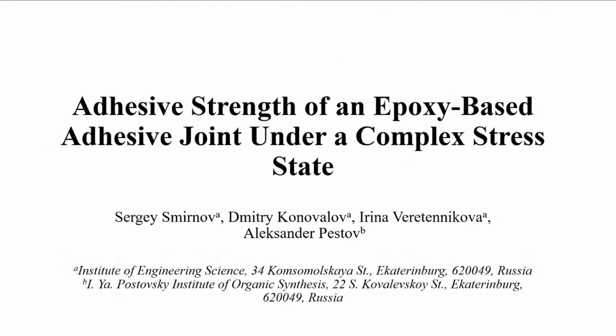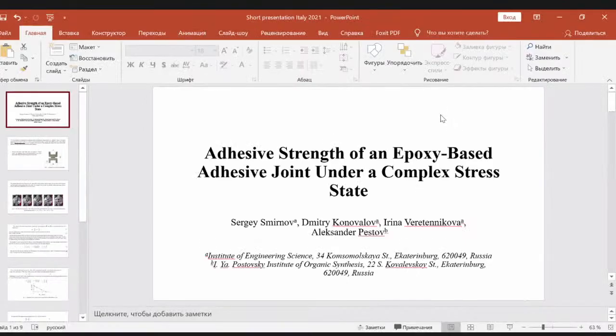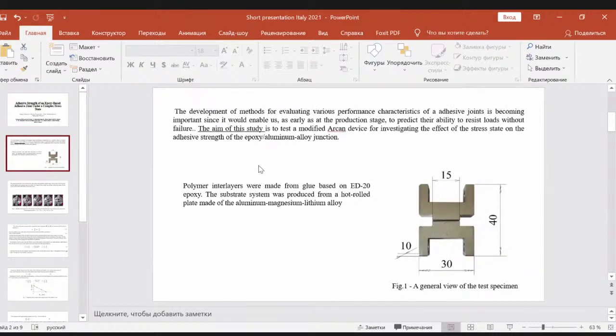We would like to present our research work, the effect of stress state on the adhesive strength of an epoxy-based adhesive joint under complex stress state. The development of methods of evaluating various performance characteristics of adhesive joints is becoming important since it will enable us as early as a production stage to predict the ability to resist loads without failure. The aim of this study is to test a modified Arcan device for investigating the effect of the stress state on the adhesive strength of the epoxy aluminum alloy junction.